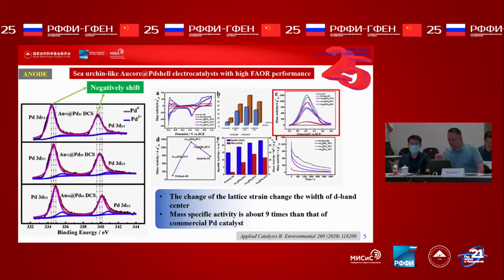XPS results confirm that the binding energy of the 3d signals is negatively shifted due to the gold introduction. This is because the gold introduced lattice strain on the palladium and leads to increased bonding between palladium and the intermediate, resulting in the prepared catalyst showing better performance. The mass specific activity is about 9 times that of the commercial palladium catalyst.